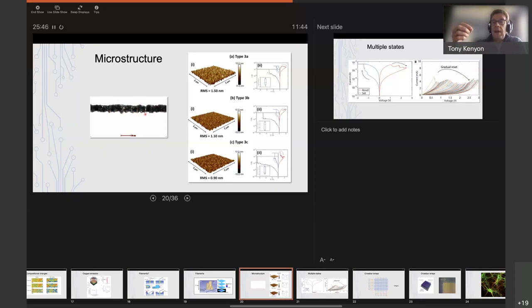These are the edges of columns. So actually, when we grow this oxide, which we do by a technique called sputtering, we create the oxide in columns, and those columns then merge together to form a continuous film. But you still have these column boundaries where there is a relatively high concentration of defects. By defects, I mean strained bonds, dangling bonds, maybe some contamination with OH groups, moisture, hydrogen. And these defects span the oxide going from the top to the bottom.